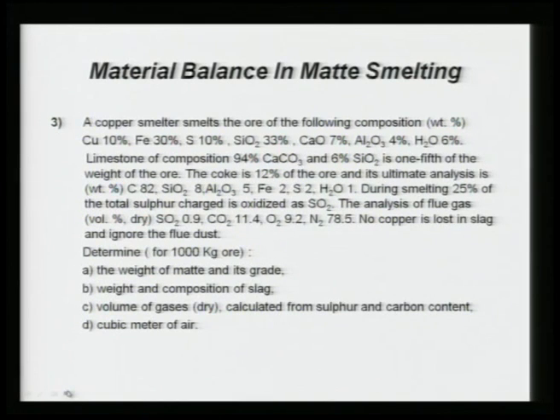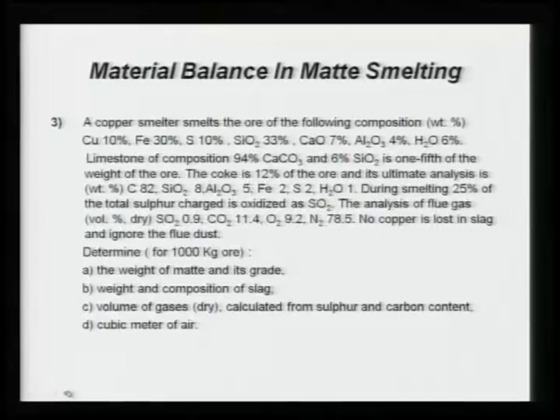As mentioned in the basics of matte smelting, flux is always used. Here the flux is limestone, and generally in most metal extraction industries limestone is used as a flux. Limestone has calcium carbonate and SiO₂, and normally some Al₂O₃ also. When heat is supplied from outside, calcium carbonate is used; but if there is a heat management problem, lime is used because calcium carbonate decomposition is highly endothermic.